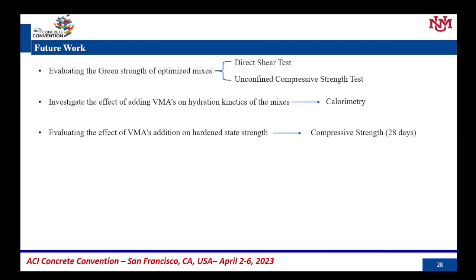We are currently working on the next phases of this project, that is evaluating the strength of the optimized mixes by two different approaches, direct shear test and unconfined compressive strength test. And also, it is very important to evaluate the hydration kinetics when you are using VMA in the mix. So we are doing calorimetry for that. And finally, we want to check the effect of adding viscosity modifier on mechanical performance in terms of compressive strength.